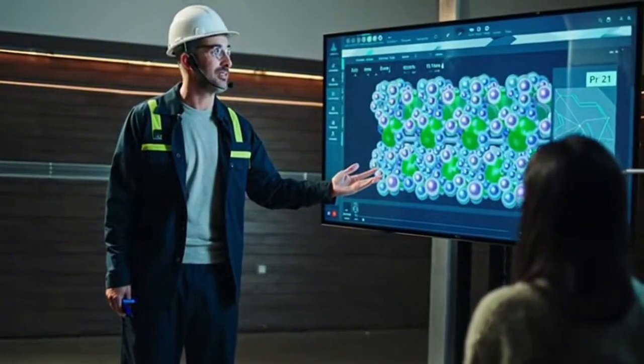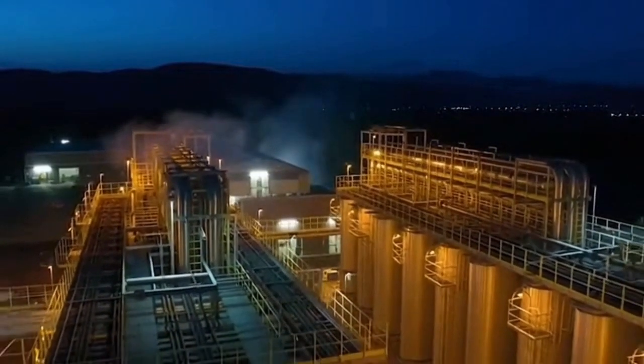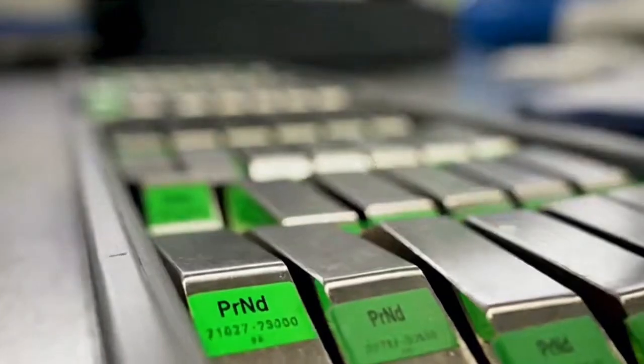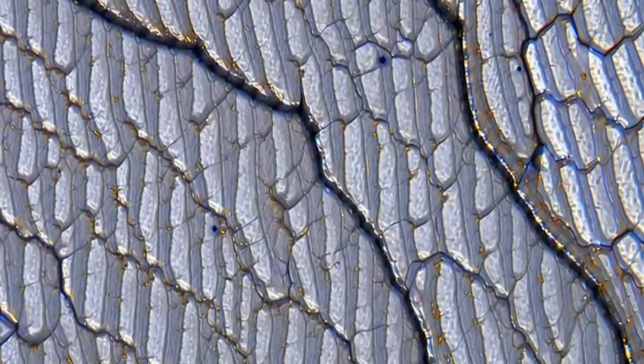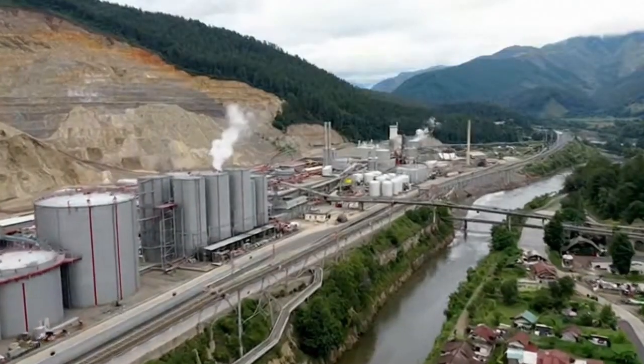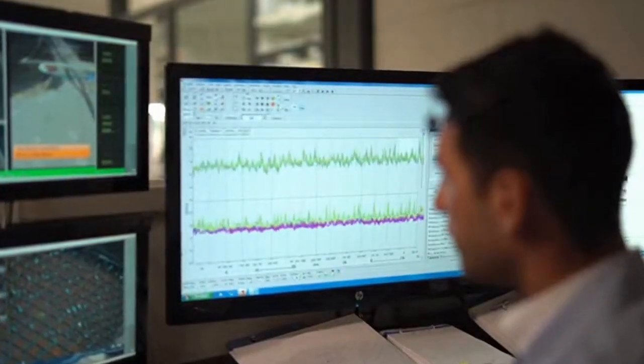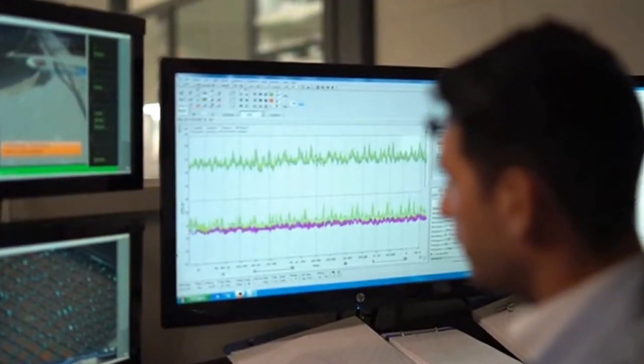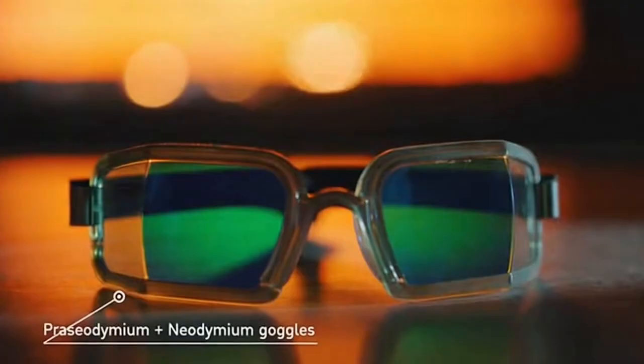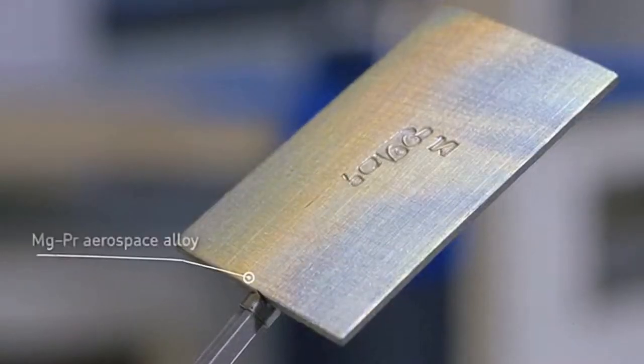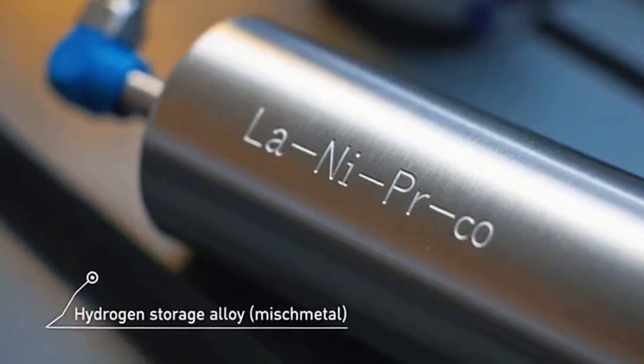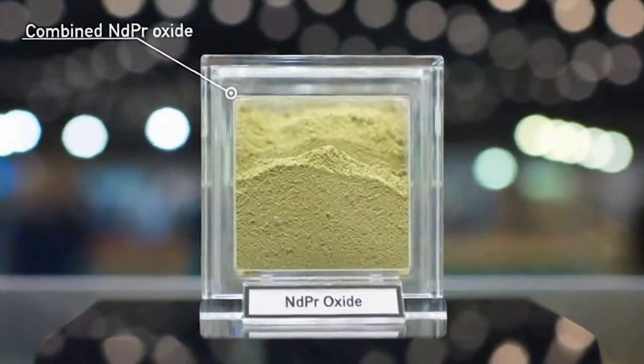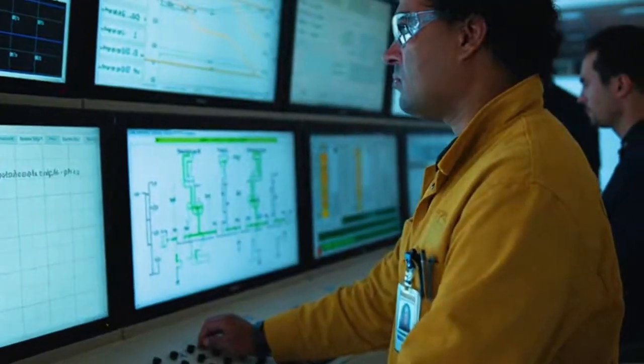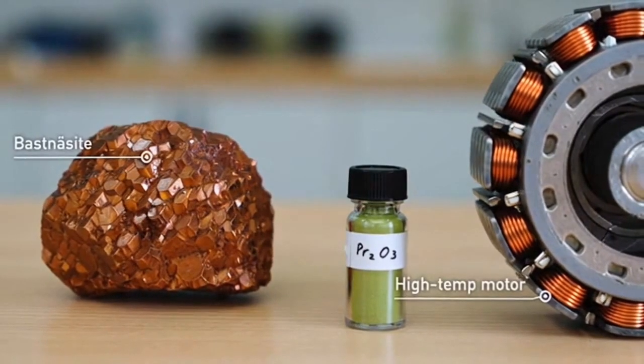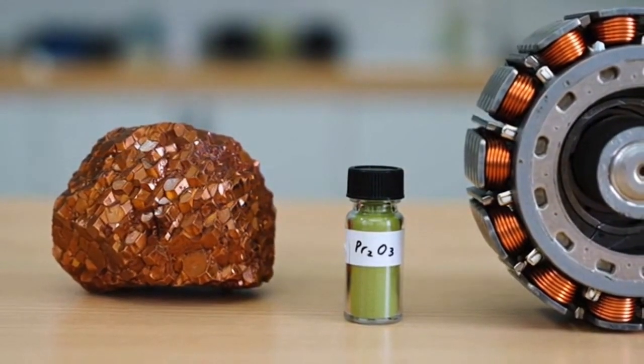Praseodymium and neodymium sit maddeningly close in every sorting metric the process uses. Their ionic radii are nearly twins, their hydration spheres behave the same, their complexes with organophosphorus extractants are separated by preferences, not chasms. So you do not separate them with a single flourish. You walk them through what looks like a city of stainless steel, with each neighborhood tuned to nudge the ratio a little more. In one bank you load, in the next you scrub, washing away impurities that came along for the ride, then you strip, persuading the organic phase to let go in a cleaner aqueous bath. Every time you do this, you are paying for tanks and mixers and pumps and instruments that do not show up in glossy investor decks because they look like plumbing. It is plumbing, and plumbing is where fortunes are made or quietly lost.